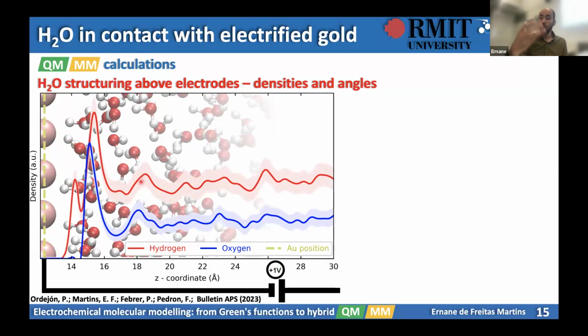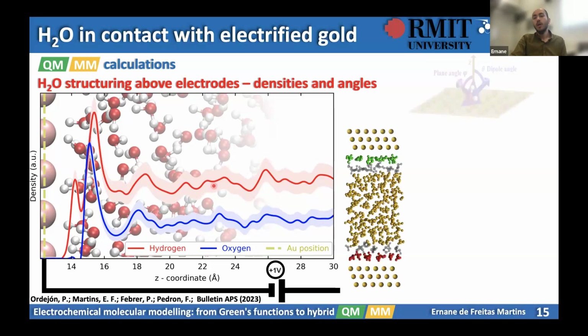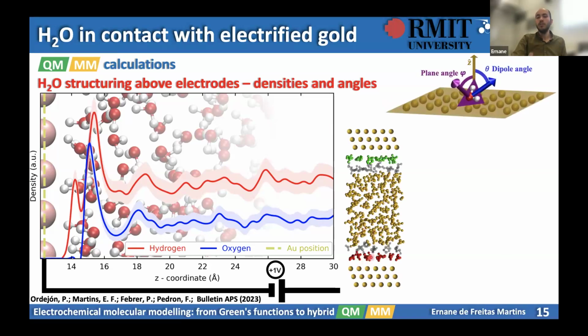We can also confirm this in terms of the angular distribution. How is the water orientation affected by the voltage we apply? We can evaluate this by splitting the water into regions: the left side, the right side, because they are different since I apply a voltage, so they charge differently, and then the bulk water in the middle. The 2 angles we can look at are the dipole angle, which is the angle between the water dipole and the normal to the surface, so the orientation of the water, and the plane angle. Is the water lying parallel to the surface or perpendicular? Those are 2 nice angles to look at.